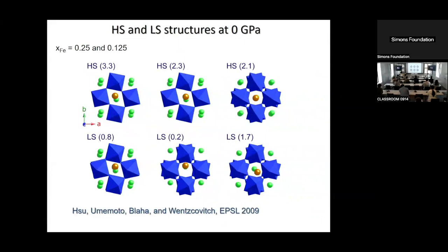SCAN is the biggest improvement that we've had so far. The agreement with the experiments is much better. When you start going to the core, then there are other kinds of questions. But in the mantle, these are non-metallic systems. Right. So that's SCAN or SCAN plus U. Some people say SCAN still needs a U, but a smaller U. I think this is to be investigated. This is one of the questions that I would investigate.